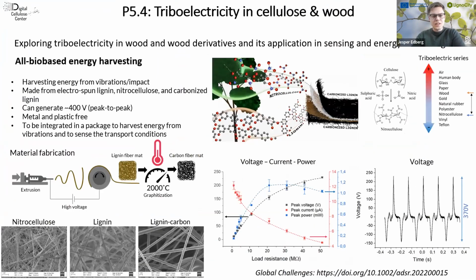So we have explored if we can use forest-based materials for these type of energy harvesting technologies. The energy really comes from the friction between two materials, and you can use quite a wide range of materials, including then bio-based materials, but it's a little bit more challenging to work with these bio-based materials. In this work, we used a chemically modified form of cellulose, which is called nitrocellulose, and also lignin to make nanofibers through electrospinning. And we made these fibers in order to get as much friction as possible, really, when we push these materials together. You also need some conductive parts in a device like this. So then we use the same lignin fibers and carbonize them.